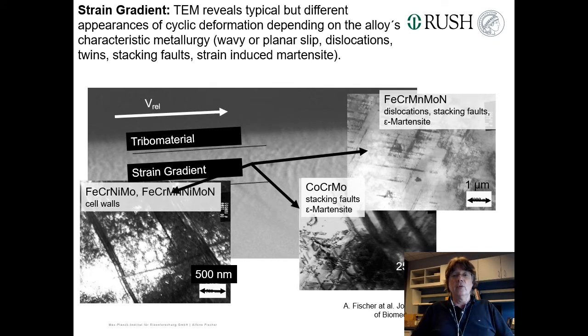The strain gradient was totally different. So with the materials which showed a very, very good tribological behavior, we only found dislocations, twins, and stacking faults on what we call discrete sliding planes, just conservative sliding down here in the strain gradient, while in the materials that generated micrometer-sized particles, we found cell walls, meaning the dislocations could cross-slide and climb and generate the cell walls, which are very well known from fatigue. And it's also known that within the cell walls, they block each other, so they can't move anymore.